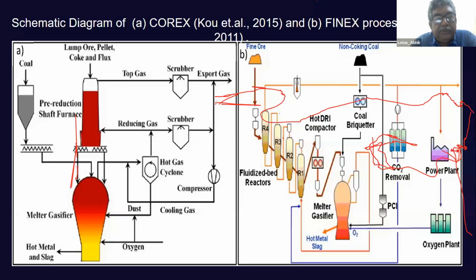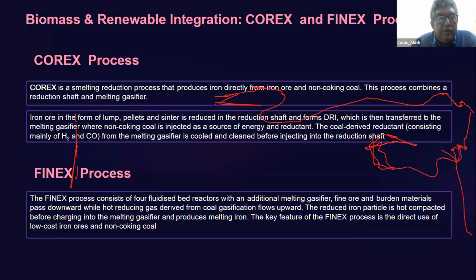This is another process. This is the Corex process and the Finex process. The Corex process is a smelting reduction process that produces iron directly from iron ore and non-coking coal. This process combines a reduction shaft and melting gasifier, similar to the previous one. Iron ore in the form of lump, pellets and sinter is reduced in the reduction shaft and forms DRI, which is then transferred to the melting gasifier smelter, where non-coking coal is injected as a source of energy and reductant. The coal-derived reductant consists of mainly hydrogen and carbon monoxide. From the melting gasifier, it is cooled and cleaned before injecting into the reduction shaft.